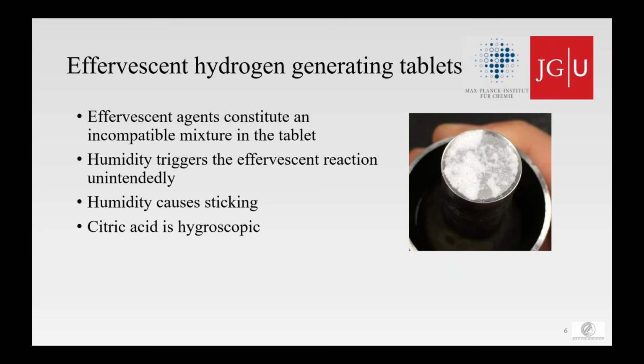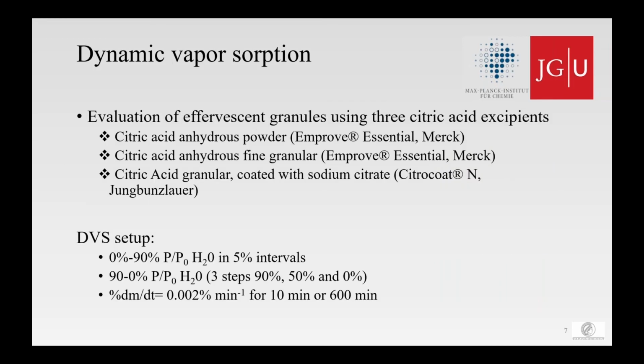So we use the dynamic vapor sorption to evaluate different citric acid products and avoid issues with sticking and stability. We had a citric acid anhydrous powder, citric acid granular, and also a citric acid granular that was coated with sodium citrate.